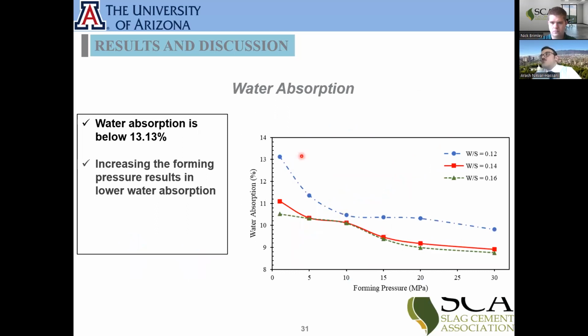So we tried to do the water absorption test. Basically, we put all the samples in the water for 24 hours and then check the water absorption rate. And this graph shows that by having a higher forming pressure, the water absorption is low. And obviously, when you push the material harder, you compact them and the porosity decreases. So you have low porosity, the water cannot penetrate, and the water absorption will be lower.